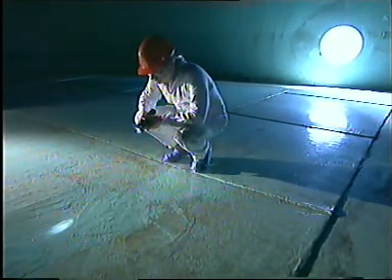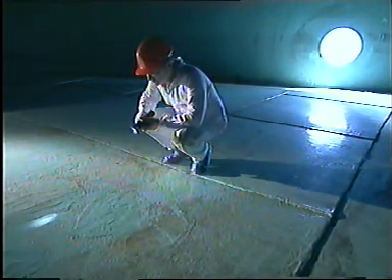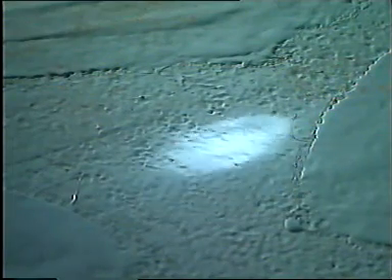After application and curing of the coating, spark testing had been carried out to identify defective areas. The few defects found were then patch repaired. This area being inspected was a heavily pitted plate on which 2 repairs can be seen. All repaired areas showed no problems. This 10-meter-long weld was cleaned for close examination. The coating was in such good condition that it might have been applied the day before.